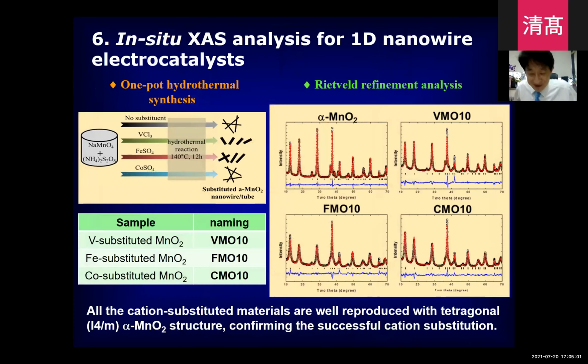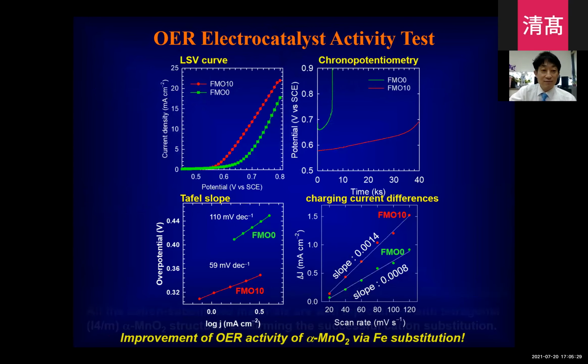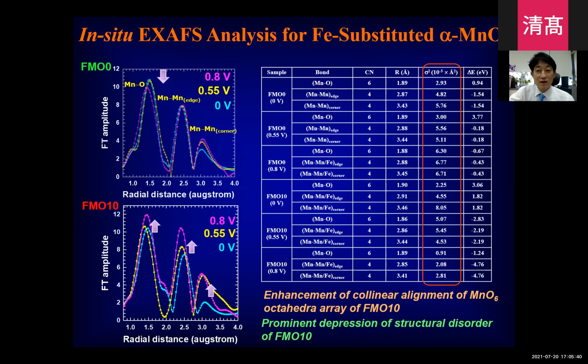This is the final topic. So long. Okay. We do the in situ XAS analysis to probe the effect of the cationic doping on the alpha MnO2 structure. From the Rietveld analysis, we confirmed the vanadium substitution, iron substitution and cobalt substitution into the manganese site of the alpha MnO2 lattice. Among those materials, the iron case shows much more promising performance as an OER catalyst. So we focused more on the operating mechanism of the alpha MnO2.